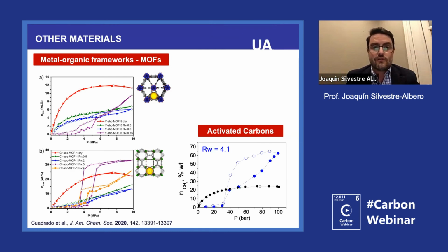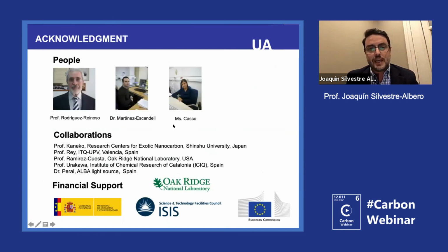So the final message is that for this specific application, the growing of gas hydrates, carbon is the best system because you combine hydrophobicity, so you are promoting the interaction of the water molecules with the methane, but at the same time, you have a proper wettability of the material. So in this sense, we have to say that carbon at the moment is the winner and is the best system.